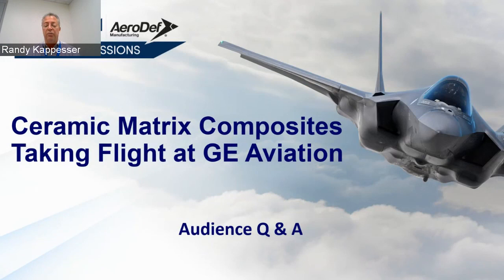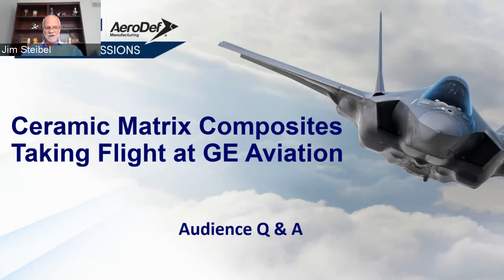Yeah, so there's a lot to that question. I may not be able to answer it all, but in terms of technical, the general aspects are right: you've got the tooling method and all the other processing aids that you might use inside the tool to help degas and control the volatiles and all the organics that are coming out in the tool. Then there are thermal cycles and how you control temperature, pressure, and environments that need to be really tailored so that you can manage the outgassing and any subsequent steps before you introduce new material, such that you have a condition that's suitable for capillary flow, because molten silicon is really capillary flow into a porous medium. And so your question is very pertinent from that standpoint. Yeah, it was very targeted. Good question and good answer.